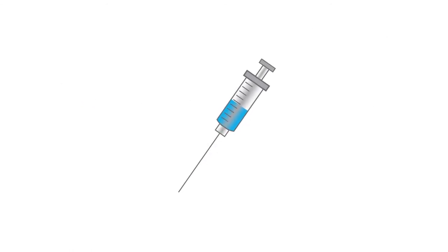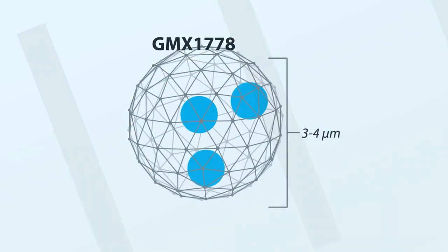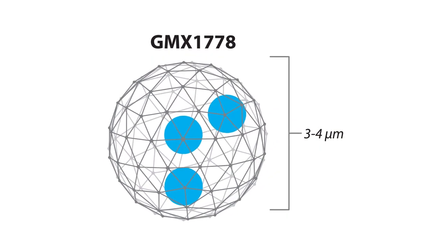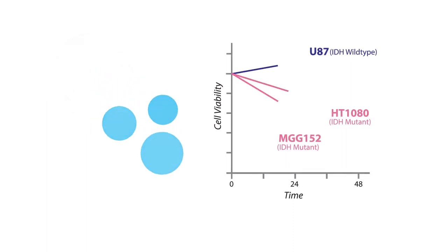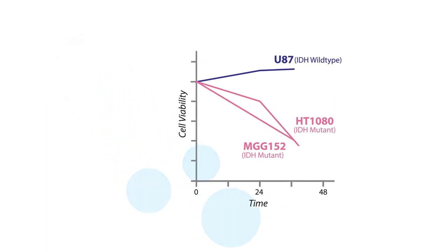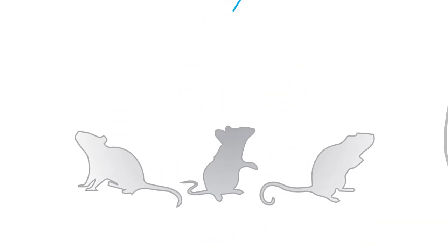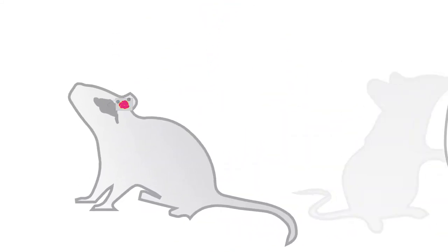For the local sustained-release formulation, we prepared microparticles from a polymer that entraps the drug inside. We showed that drug is slowly released from these particles, only killing mutant cells and not others. We then applied these microparticles to brain tumors in mice.